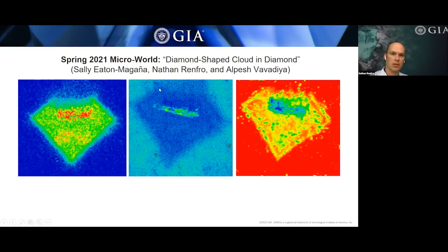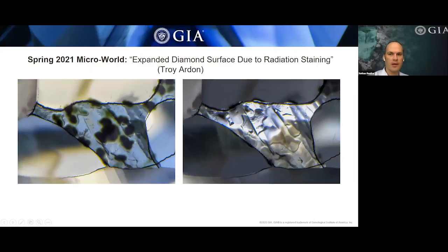There was also a map in the center image, which was the H3 defect distribution, which showed that it was much higher outside of the cloud area. And then the image on the right showed the Raman map of the diamond peak itself. And so that showed that the diamond peak was stronger in the non-cloud area as opposed to the defect area in the cloud. So quite an interesting stone there.